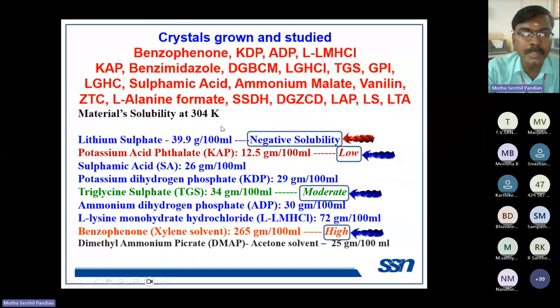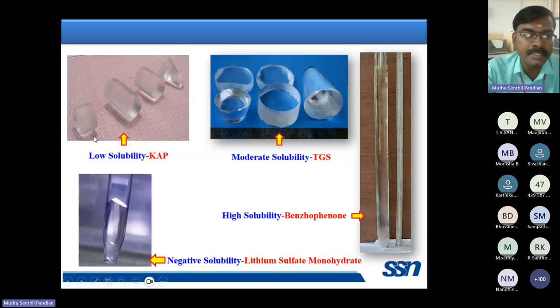already grown. We are able to grow organic, inorganic and semi-organic categories. We can also grow crystals from low solubility materials like KAP, 12.5 gram per 100 ml, moderate solubility like TGS, 34 gram per 100 ml, and very high solubility like benzophenone, 265 gram per 100 ml. So all categories are possible by this unidirectional solution crystallization method. This is a low soluble KAP and moderately soluble TGS, and this is a very highly soluble benzophenone single crystal, and this is the negative soluble lithium sulfate. These are all positive soluble materials, and this is the negative soluble material.